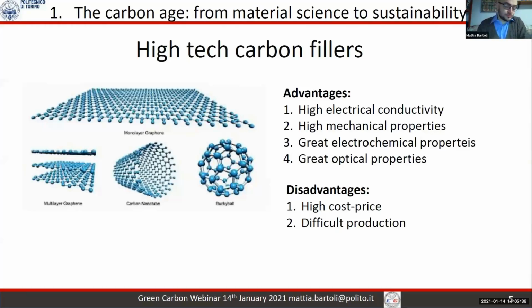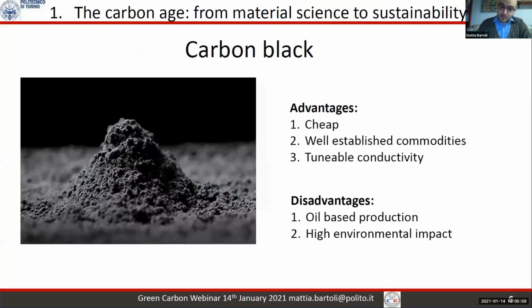So when we started to move around, search for investors, and talk with companies about our good results with carbon nanotubes and other materials, they said to us, okay, but the carbon composite field is different. And we found that the carbon composite field is dominated by another material, carbon black. Carbon black is the leader. When we are talking about composites that contain carbons, the first material that everyone uses is carbon black because it's cheap, because it's largely produced, because it can be tuned to selectively enhance the electrical properties. The main drawback of carbon black is represented by its nature. It is produced from oil residues, so the environmental impact is quite high.